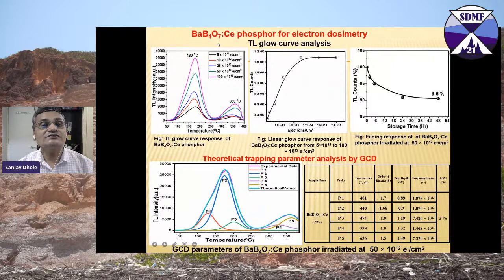So this is the barium borate doped with cerium phosphor for electron dosimetry. Again, I will just let you know the response curve where you can have the fluence level 10 power 12 to 10 power 14 electrons per centimeter square. This is quite linear. And further, as you go on increasing the fluence, it goes to saturation.